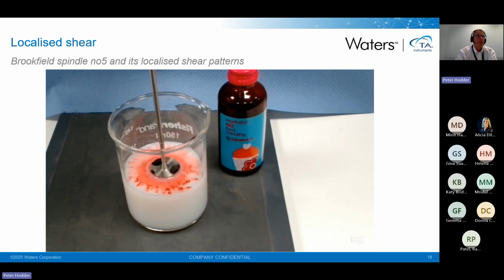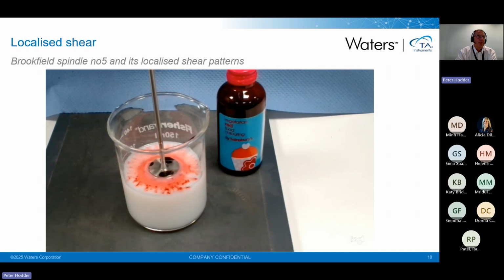So that's now been stirring for quite some time. As you can see, the red food dye has spread on its own accord using the Marangoni effect. But what I'm really focused on is where the spindle is, and what you can see is as it's rotating there is a white band directly in contact with the spindle itself. Then there's a slightly bigger red-pink ring around it, and if you look close enough in the white band and at the edge of the pink, you'll notice some droplets of food dye rotating. That's really indicating what I wanted to see, which is that there's a very localized shear around the spindle, and hence why using a spindle on a Brookfield in an infinite beaker like this really just shows that there's a localized shear, but you don't really know how much material you're shearing.